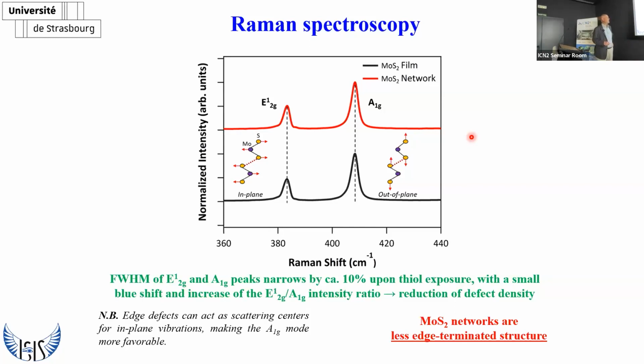And actually, we focus on the full width at half maximum of the E12G peak and the A1G peak. And we saw that upon thiol exposure, it narrows down. And there is also a blue shift, an increase of the ratio between the two. This, again, is an indication of the decrease of the defectiveness within the film. In particular, what we found with Raman is that most of the defects are at the edges and not really on